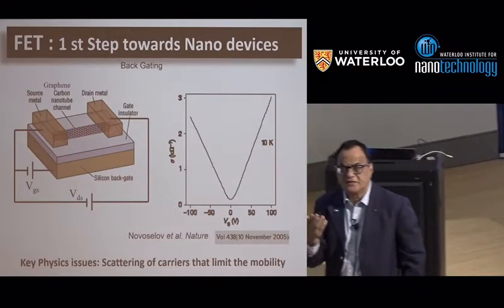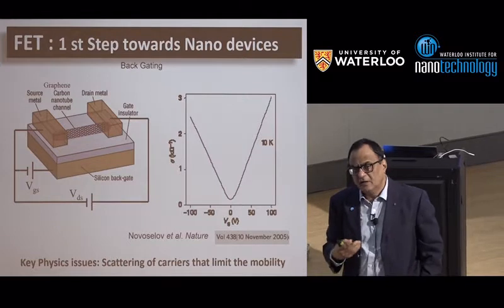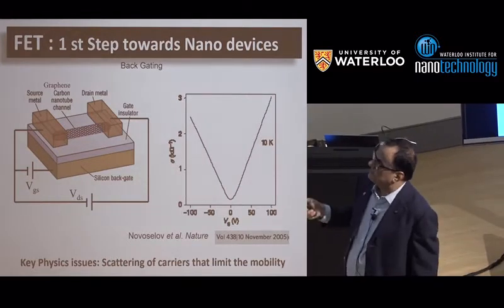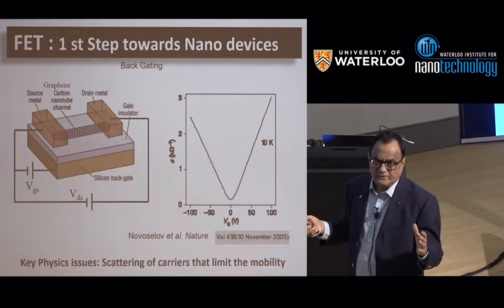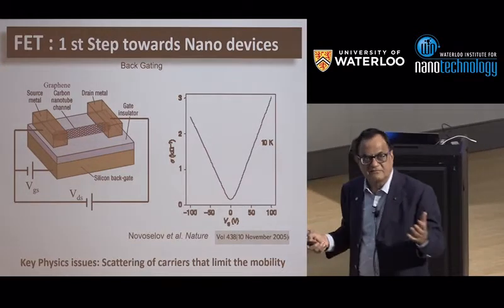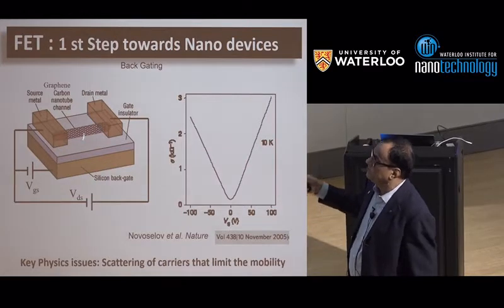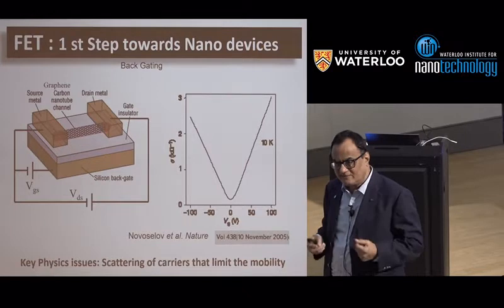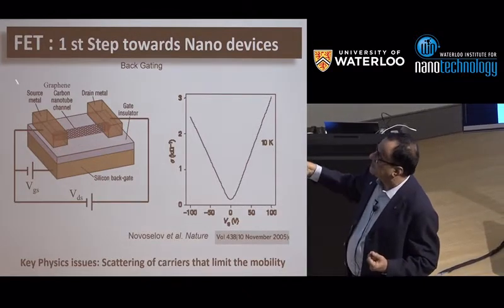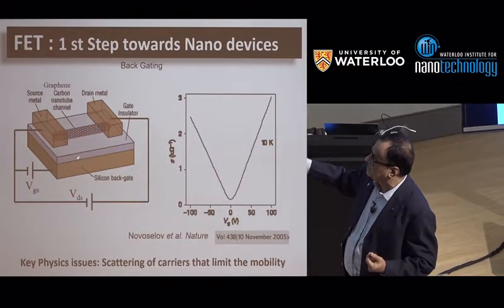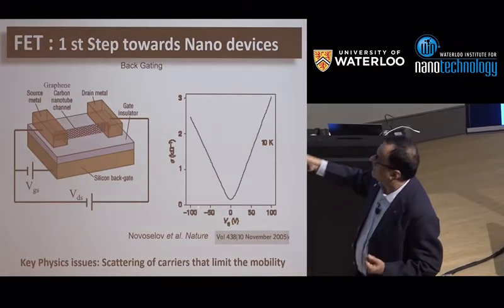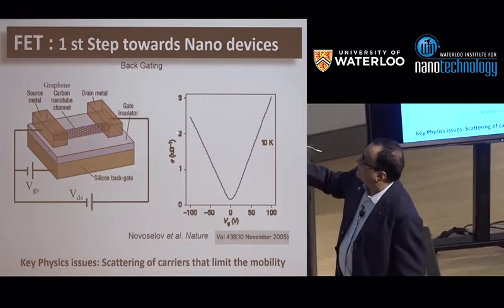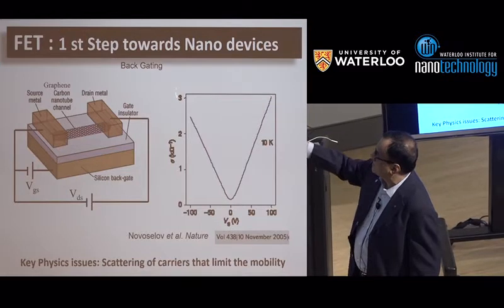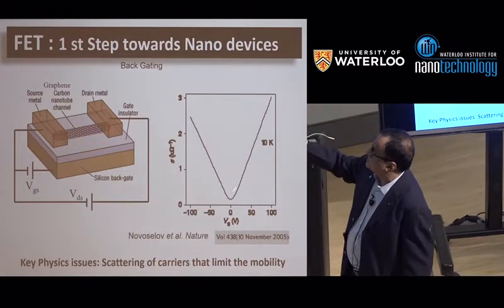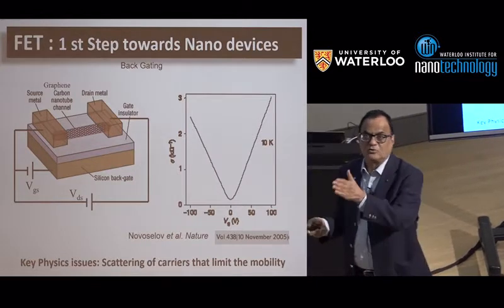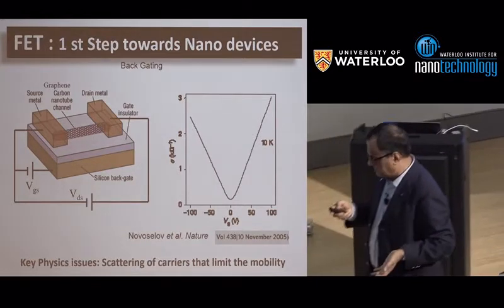So I'll give you just two examples of this from our work, and literature has other examples. So the first step is that when you make a 2D material, you would like to make a device, and the simplest device is the field effect transistor, which is what you do. It's like a hydrogen atom of the devices. You immediately make a field effect transistor: source, drain, you have a gate, let's say 300 nanometer SiO2, and then you have a back gate. And this is from the very early work, 2005, showing conductivity change as a function of back gate voltage. This is the Dirac point, and this is what gives you the conductivity. And it is symmetric on the electron and hole side, something shown almost 13 years back.